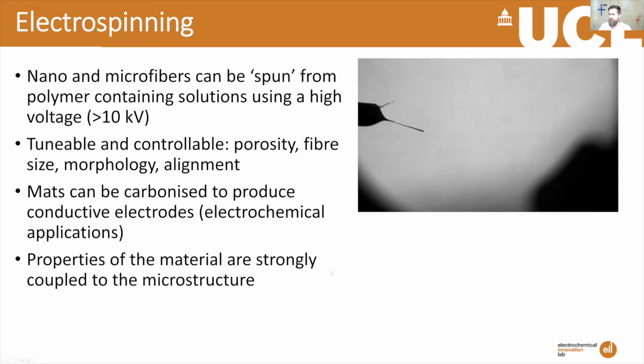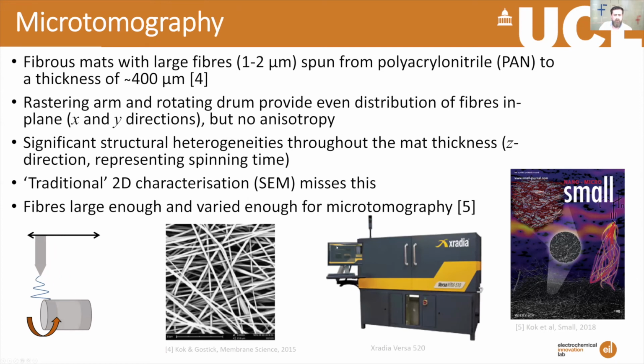However, there are things you can do to tune and control the microstructure and the properties of these things. So you can tune the porosity, the fiber size, the morphology, even the alignment. I'll talk a bit about that in a second. And then once you've spun these polymers, you then carbonize them to give you a conductive, freestanding electrode as well. And the properties of the material are very strongly coupled to the microstructure, as is often the case in electrochemical devices. Okay, so I'll start off with a bit of microtomography on these materials.